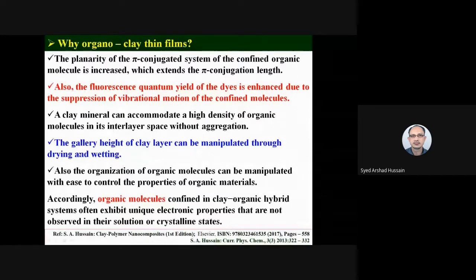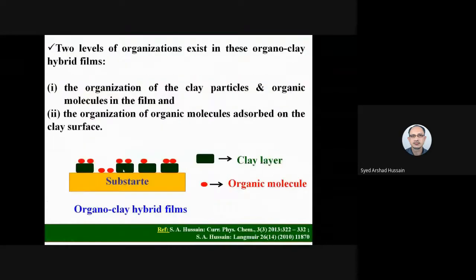Another thing, one can play with the clay layer gallery height. That means one can play with the thickness or gap between the sheets within the clay layer by simultaneous drying and wetting. In this way, one can play with the organization of the material and hence its optoelectronic behavior. Therefore, organic molecules confined in a clay-organic hybrid system exhibit unique optoelectronic behavior that is not observed in a pure organic system.